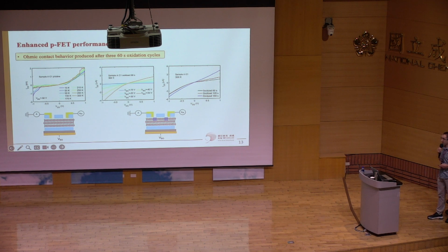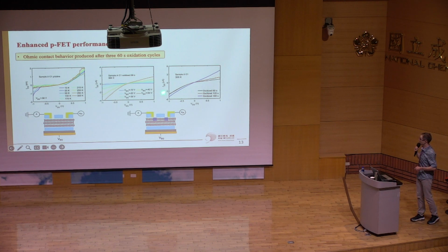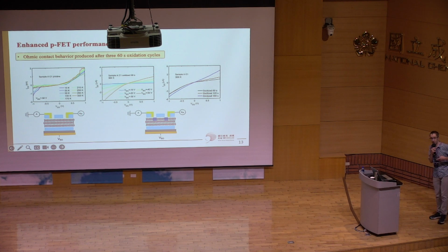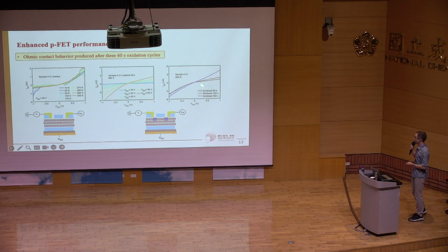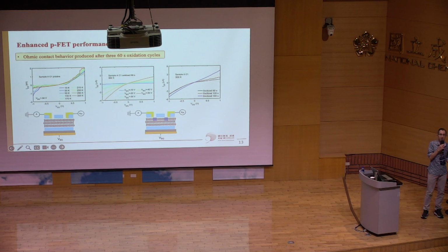And so we just repeatedly exposed the sample to oxygen plasma 60 seconds at a time, and we found that after 180 seconds, so 3 times oxidizing this device, we get this much more linear trend. Now there are several possible reasons for that. One is you've reached a sufficient doping level. The other is if there's any directionality associated with the oxygen plasma process, then